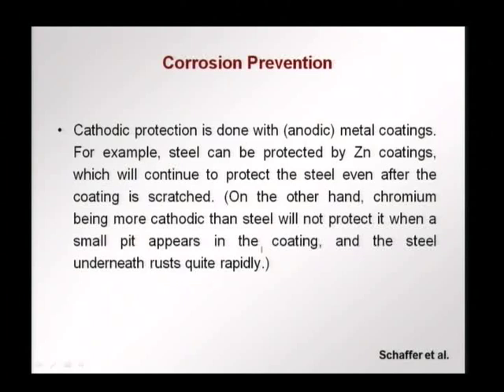Chromium plating is also used many times, but that will not protect the steel much, because chromium is more cathodic than steel. When corrosion starts, a small pit appears in the coating, and underneath it you can have the steel corroding, and unfortunately you will not see the corrosion occurring because the chromium plating is at the top. Eventually you will find that corrosion has been occurring and you have a loss of material. So, chromium plating, though it is used a lot, is not a good way to provide cathodic protection. Zinc coatings have been used for a long time and they are very efficient in giving cathodic protection.